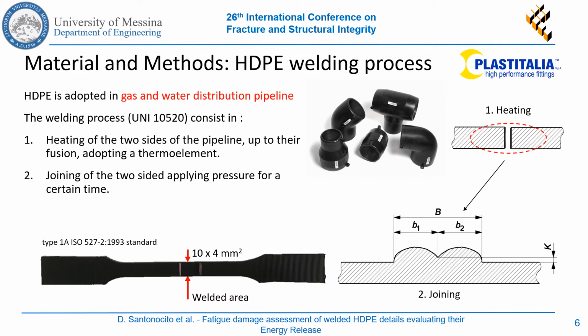The tested specimens are retrieved directly from the pipe, according to the geometry of the ISO standard for plastic material testing. The weld bead was removed by milling the surfaces.